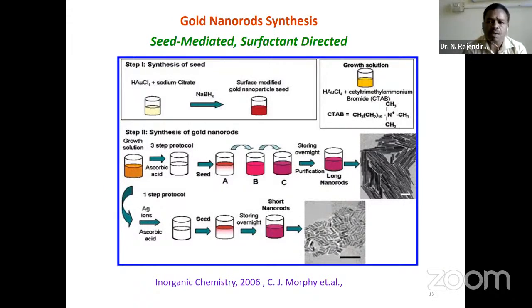Seed solution means the particle is of very small size. And for the second solution, he prepared a growth solution. That is, he added auric chloride with cetyl trimethyl ammonium bromide surfactant, and added ascorbic acid for the preparation of growth solutions. So he added a mild reducing reagent. By mixing the seed as well as the growth solutions, you will get long nanorods. So the formed particles are anisotropic in nature.